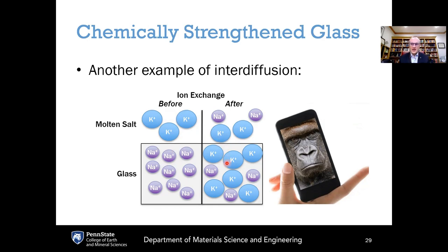These are diffusion of ions, so diffusion of charged species, and in order to maintain charge neutrality, there has to be a net zero flux here. These larger potassium ions have the same charge as sodium, but they're much bigger, so they don't quite fit into the structure as comfortably as the sodium did. They want to expand the surface of the glass. The interior of the glass doesn't want it to expand, and so it pulls the surface of the glass into compression. So if you want to break a chemically strengthened glass like Gorilla Glass, you have to overcome not only the intrinsic strength of the glass, but also the compressive stress profile provided by this ion exchange process.